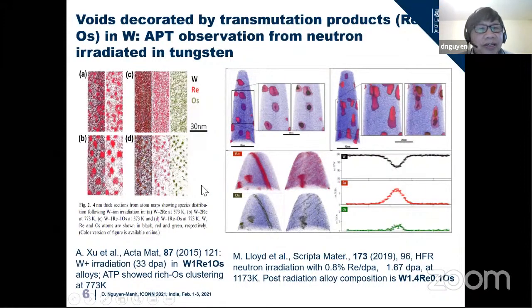What is important here is that this atom probe tomography picture is for ion irradiation, but it shows that if you have the presence of both rhenium and osmium, then the behavior of precipitation is quite different. If you have only rhenium in binary alloys, then rhenium is the main precursor of precipitation. But if you have osmium coming in, then you have mainly the effect of osmium in precipitation inside the radiation-induced precipitate. The small amount of osmium becomes very important. So we try to understand what is happening here.